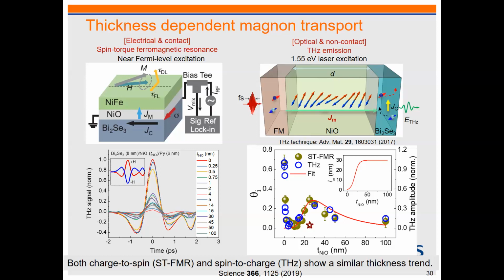Why nickel? Why not copper or iron? This is a good question. Typically, this always ends up with what is available in the lab. Many people ask this question. Also, I ask many questions when I go to APS or similar conferences: why do you use this material? How do you think about it? Because it's in my drawer, so easy to put in. Nickel oxide is an antiferromagnet, and people measure exchange bias using nickel oxide. We understand these antiferromagnets very well, and I did nickel oxide as part of my PhD, so I know this material very well. It has surprisingly the highest Néel temperature among many other materials. So we know this will work at room temperature.